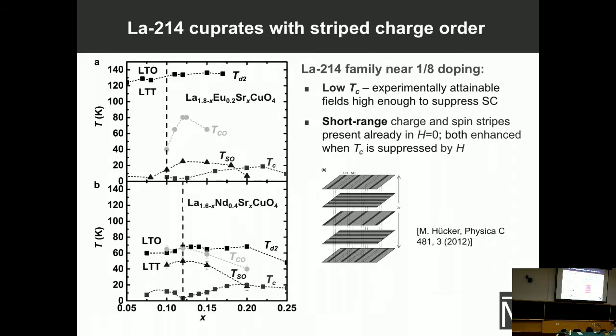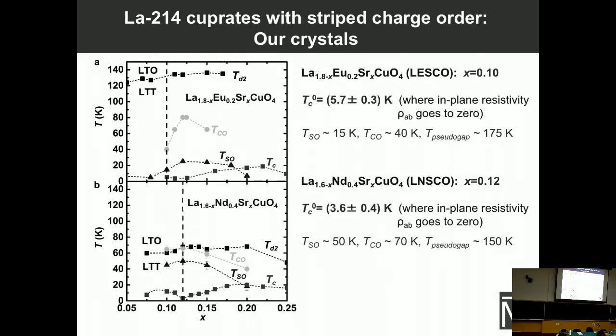Okay, so the materials that we have looked at are from this family, lanthanum-based cuprates, which have, as was already noted earlier today, low Tcs. So these are the two materials. Their phase diagrams are shown, and in these materials, the Tcs are low, as you can see with these red symbols. And it is also known that in zero field, around this 1/8 doping, charge orders develop in the form of stripes, which alternate with the charge-poor antiferromagnetic order, the spin stripes. Shown here is a sketch, and the arrangement of these stripes is rotated by 90 degrees from plane to plane. In reality, these are short-range stripes, so the correlation length in these materials is of the order of 100 angstrom. The vertical lines show the dopings of the two materials that we looked at.